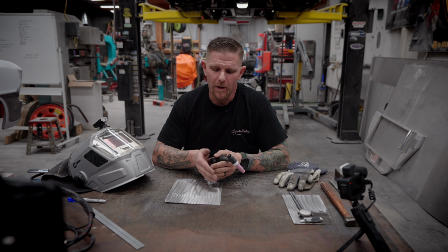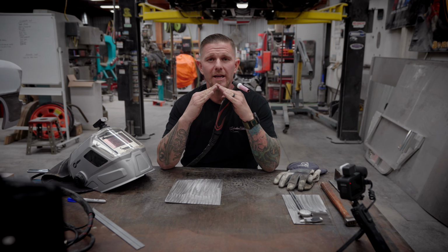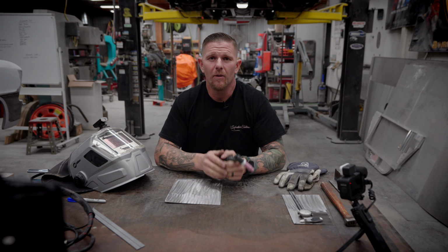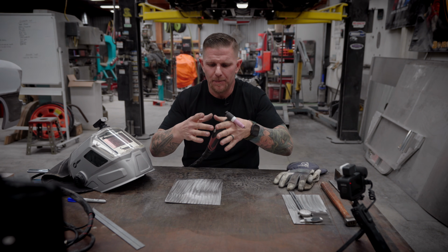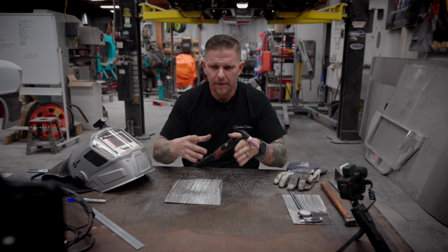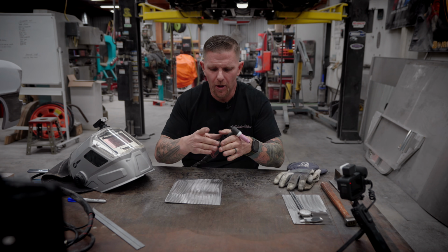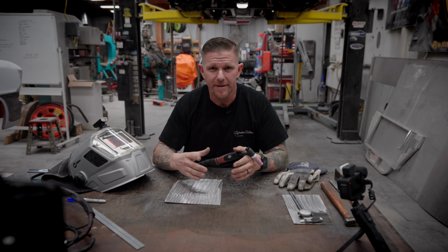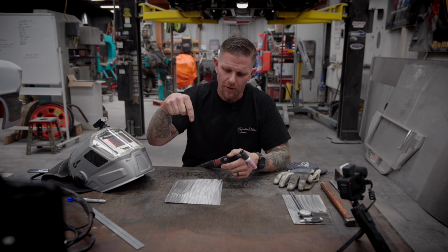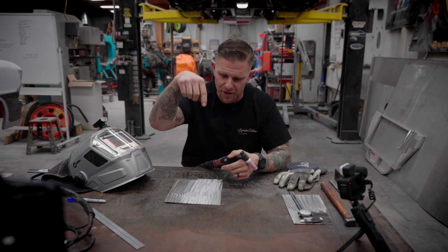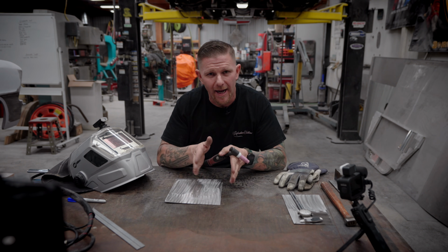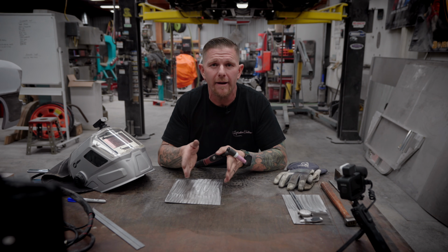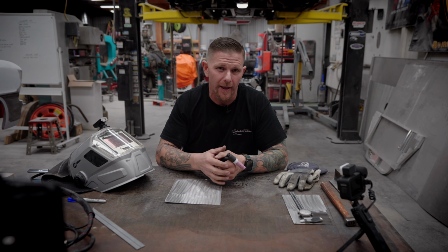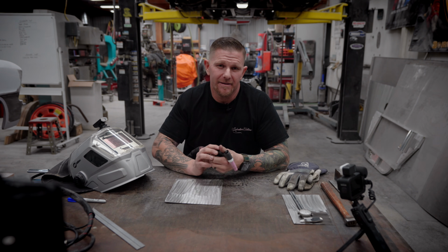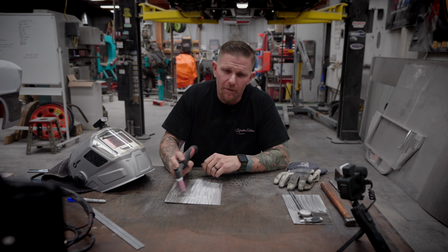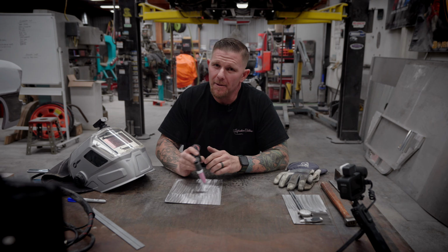Sheet metal, we want to grind the tungsten where it's more of a dulled point. What that's going to do is it's going to keep the pool and the arc length more controlled out on the surface. If you have a sharp point, it's going to be putting a lot more amperage down into the metal, and you're going to end up with the sheet metal wanting to blow away from itself when you're doing a joint. The distance that you travel over the sheet metal, you want to be really close.